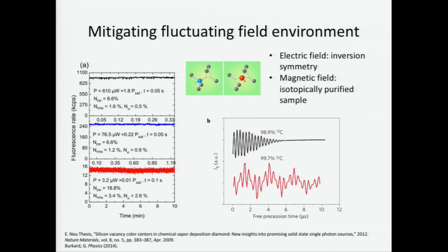And the second part is the magnetic field fluctuation, which is relevant to the spin coherence. Actually, the very reason why color centers in diamond are popular is because of the maturity of diamond material technology. Diamond is all made of carbons, and if you grow your sample very well, you can isotopically purify the diamond to have almost all carbon-12, 99.7%. If you do that kind of engineering, compared to the natural abundance of carbon-13, carbon-13 is the killer for the spin because it has a spin.